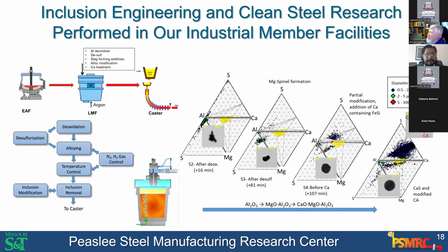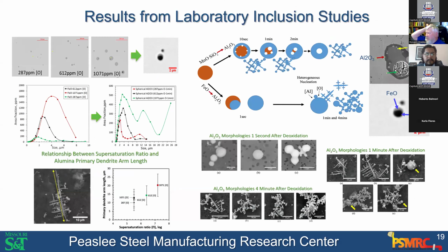So the other kind of work we're doing is inclusion surveys for clean steel, evaluating the evolution of inclusion morphologies over time. These studies are done largely in our laboratory where we have upwards of 500-pound steel melting capacity in an air melt induction furnace. And we've actually been able to track the evolution of inclusions and their behavior from their inception in the electric furnace all the way through the final product.